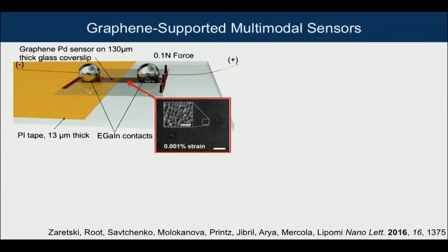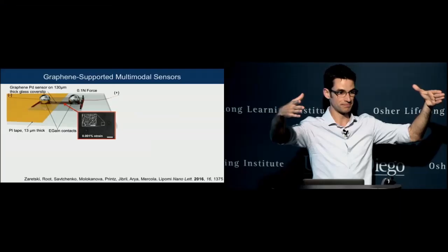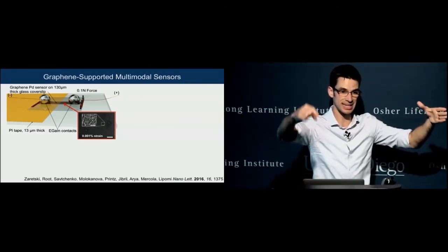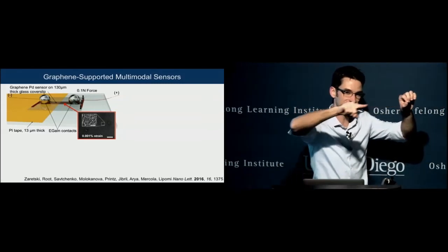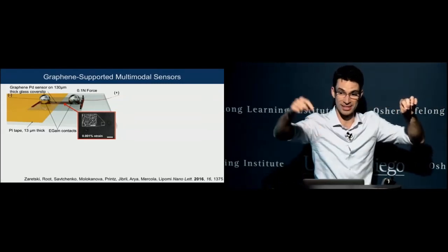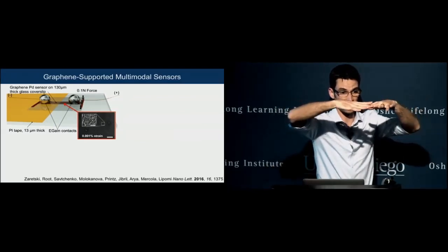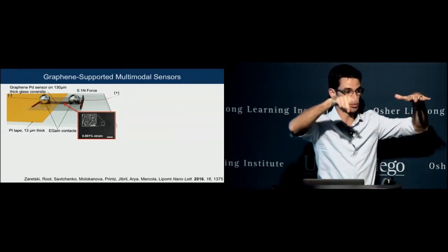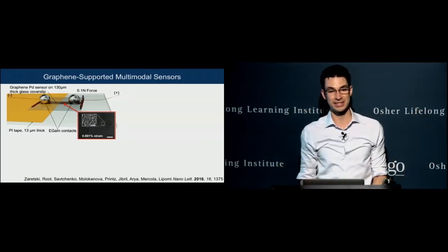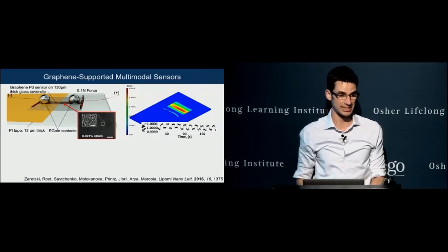This is a schematic drawing of a piece of glass with a thin piece of tape. It's a plastic tape that's heat resistant, called Kapton, and you can buy it at a hardware store. It's 13 microns. It generates a very small step between the step edge of the tape and the glass slide. If you take your graphene film with the metal nanoparticles and put it right on the step and press down, you generate a very small strain right at the edge, where your film is being bent. That generates a strain that's 1,000th of 1%, and we can measure that.